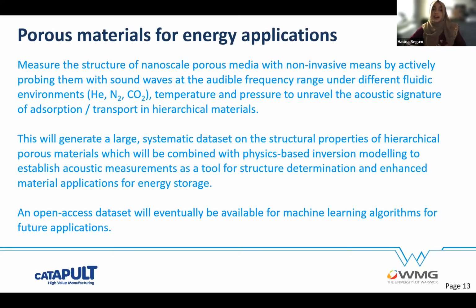And if anyone has any ideas, then please let me know. This is where we come up with the idea that we'd like to measure the structure of nanoscale porous material with non-invasive means. So we want to actively probe them with sound waves at the audible frequency range under different fluidic environments like helium, nitrogen and carbon dioxide, using different pressures and different temperatures to unravel the acoustic signature of the adsorption and transport in hierarchical materials.